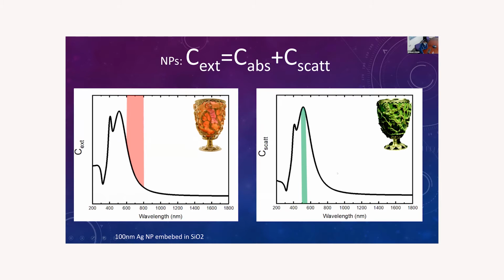On the other hand, if the light is coming from outside the cap, we observe this green color that is due to the scattering of the nanoparticles. If we observe this scattering spectrum, we can see that the main contributions to the scattering are around 500 something, that is the green region of the spectrum. So that's why we can observe the different colors in this kind of structure.